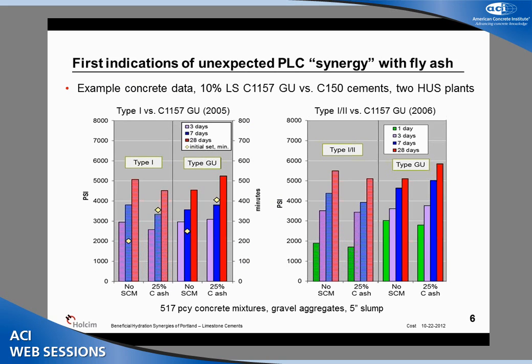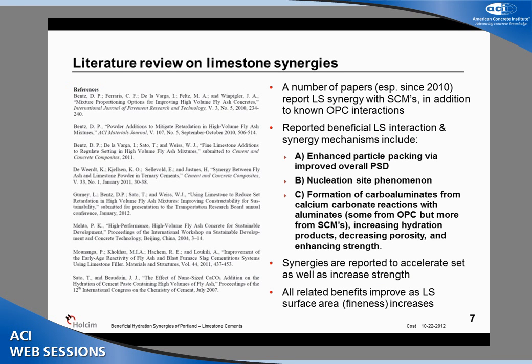This is just an example of some concrete data from our initial experiences with this material that kind of led us to investigate these synergies. And this is 2 different plants represented from 2005, 2006. What we're seeing, even in plants where the response of the ordinary Portland cement with replacement of Class C fly ash was not very stellar, and that was true for both of these plants. When we took the same clinker and made Portland limestone cement, all of a sudden this trend reversed, and we started seeing better behavior, higher strengths at all ages with the same percentage of fly ash replacement. Now, this led us to think that this was something that we should better understand and take advantage of.